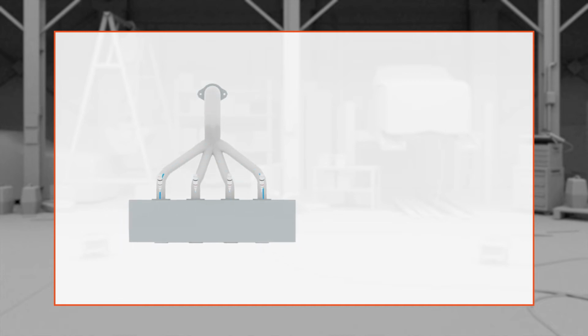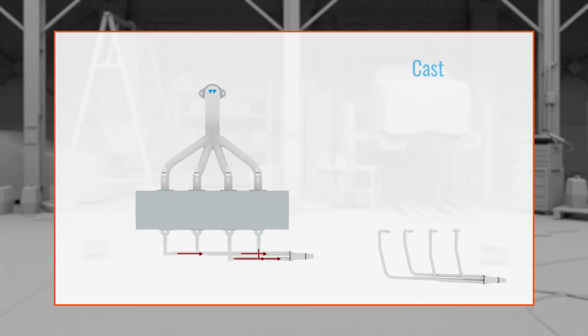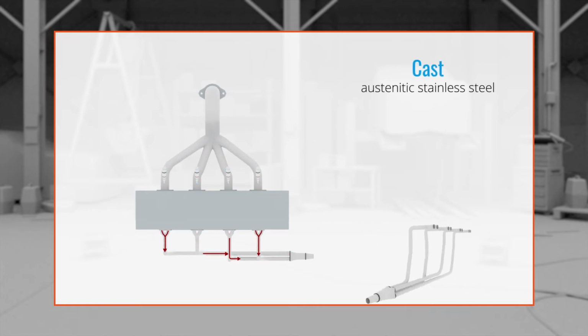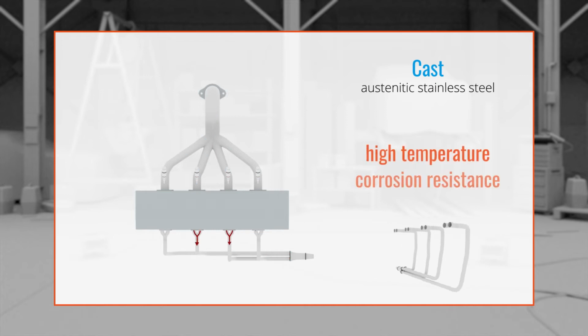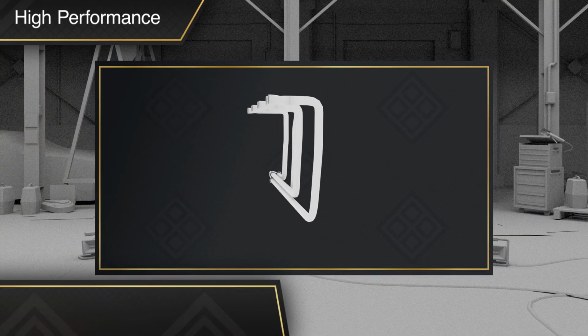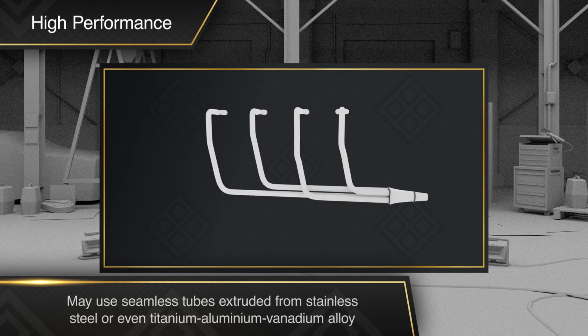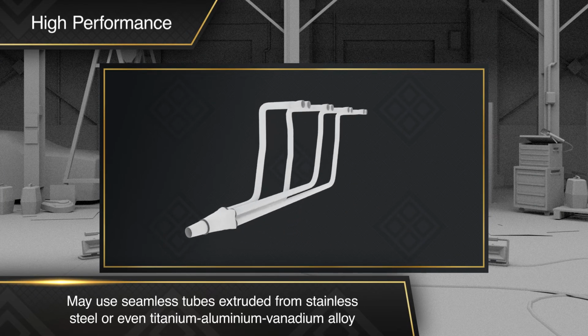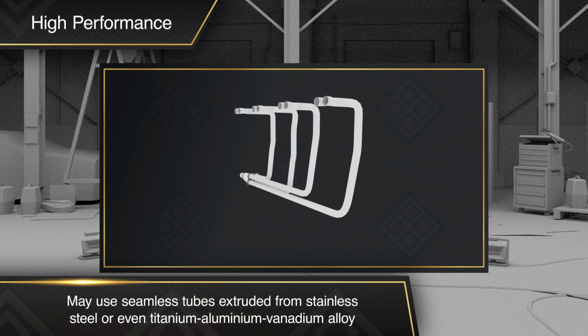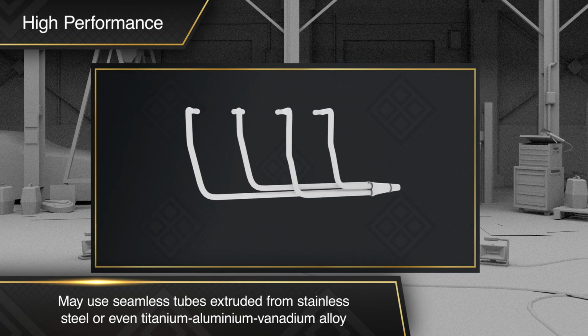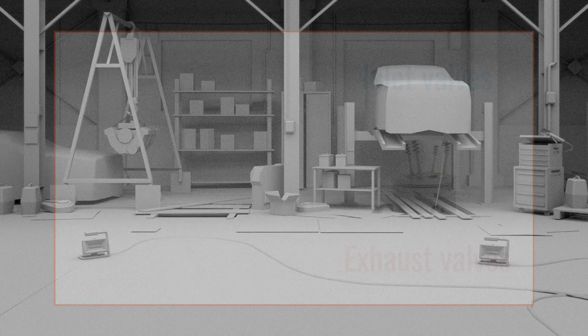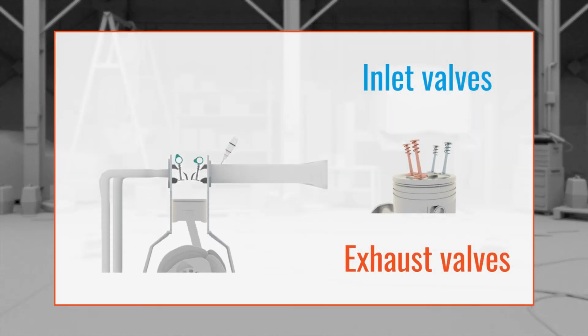The exhaust manifold routes the hot pressurized exhaust gases away from the cylinders after combustion and eventually to the tailpipe. The exhaust manifold is typically made from cast austenitic stainless steel, where high temperature corrosion resistance is the main priority. High performance engines may use seamless tubes, extruded from stainless steel or even titanium, aluminium, vanadium alloy, which is around half the weight.